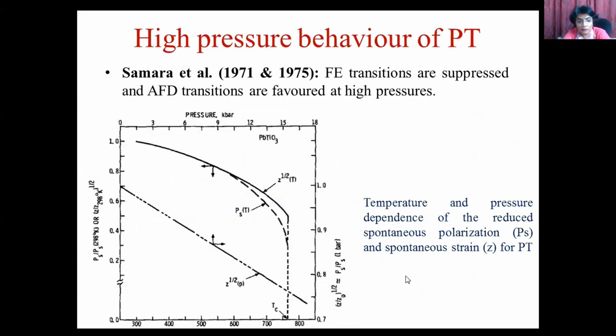So, talking about the high pressure behavior of lead titanate, there is a very classic study by Samara et al. in which he has studied a number of classic ferroelectric materials, in which he has found that the ferroelectric transitions are suppressed at high pressures, whereas AFD transitions are favored at high pressures. So he categorized lead titanate in the ferroelectric materials, and its phase and its polarization was found to be decreasing with increasing pressure.